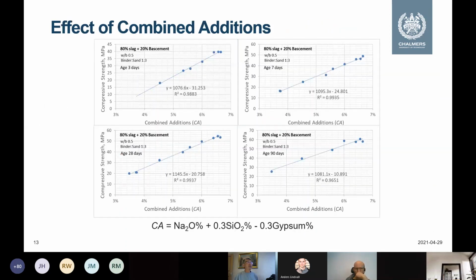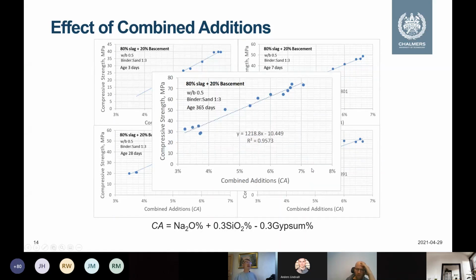Then we also found a very interesting relationship between this sodium content and silicate content, or gypsum content. So you can see that this is 3 days strength. So we have a very good curve. We call it combined additions, with a very good correlation. And this is 7 days, 28 days, 90 days, and even 1 year's results. You can see that the correlation is quite good.